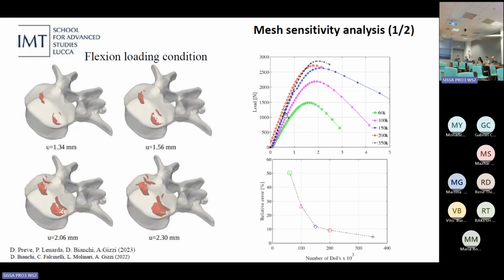Here we can see that in terms of peak load, we have a convergence in the load displacement curves as we increase the number of degrees of freedom, and this is confirmed also by the computation of the relative error with respect to known values of the peak load from numerical experimental results of the same loading condition. So we can see this kind of convergence.